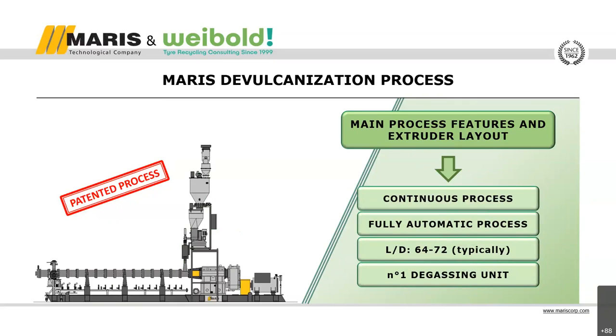The typical layout of the process is quite simple. There is a gravimetric feeder that feeds the extruder in a constant and continuous way. The entire process is fully automatic, so you can control it easily. The length of the process zone in terms of L/D is typically 64 to 72. The ratio L/D is the ratio between the length and the diameter of the barrel. The process includes a degassing unit, which is able to evacuate all the gases that are formed by the process.